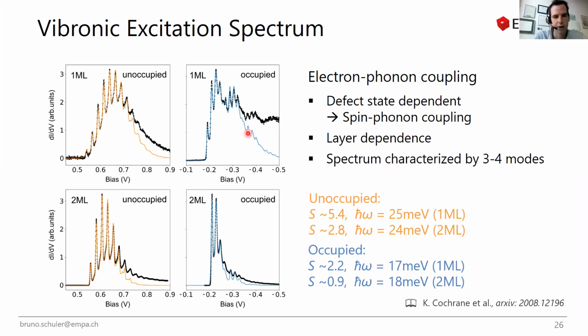And here the occupied one is different. So first of all, we see different modes which become more dominant, and we see that the Huang-Rhys factor is a little bit smaller. But this really tells you that there is some sort of spin-phonon coupling going on, because again, we have these spin polarized states, which are quite similar in terms of their spatial wave function, but they carry different spins. So the lattice reacts differently to those.